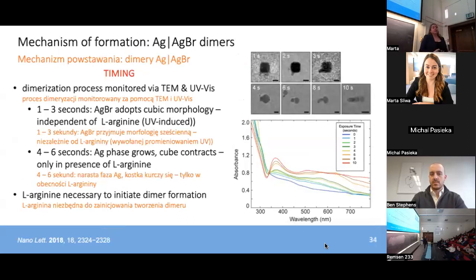Having established the necessity of the oleate ligands to the stabilization of those hosts, we then moved on to investigate the mechanism of how the dimers were formed and asked ourselves, how fast do these dimers grow? And what is the timing of this process overall? So we found through carefully running these experiments, stopping them at 1 second intervals and taking a look at the products via UV-vis and under the transmission electron microscope, that this process occurs over a time scale of roughly 6 seconds and in 2 very distinct phases.